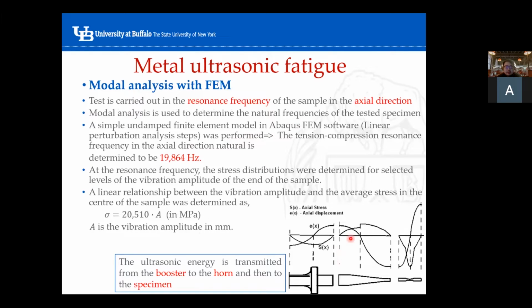So actually, we have to do a modal analysis with finite element to find the natural resonance frequency of the sample in the axial direction. So basically, we build up an Abaqus FEM software and perform these steps, tension-compression resonance frequency in the axial direction. And we figure out that the resonance frequency is around 20 kHz.